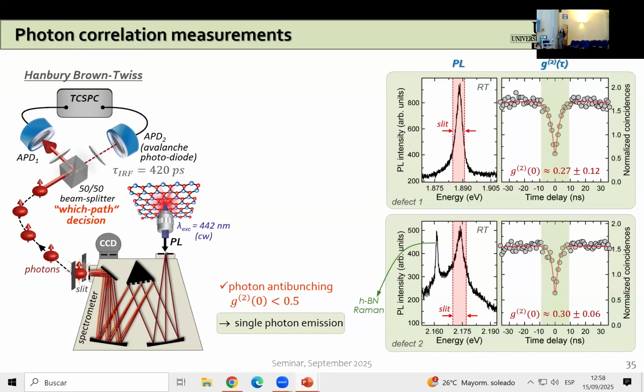So what we then also wanted to prove is that we again have single photon emission from this system, and we used, as I said before, a Hanbury Brown and Twiss interferometer, and we see that even at room temperature, most of these lines coming from the atomic defects do actually show such a reduction of coincidence rate at zero time delay. And when we perform the correction for the background and temporal resolution of our system, we again obtain the g2(0) values, which are well below this 0.5 threshold.